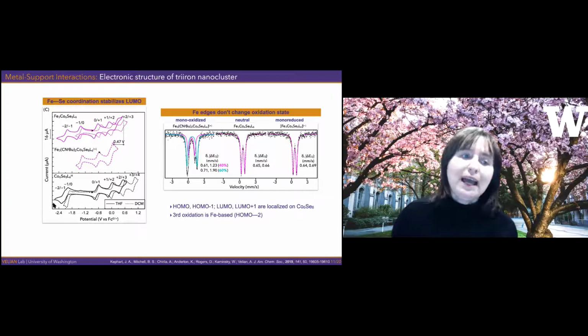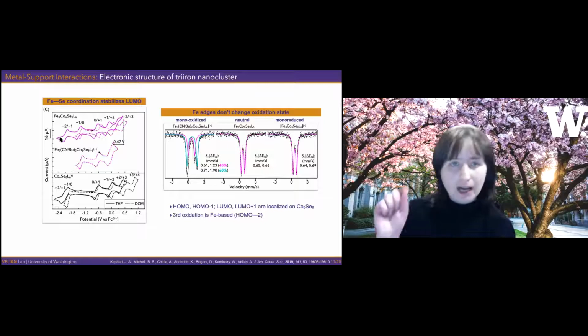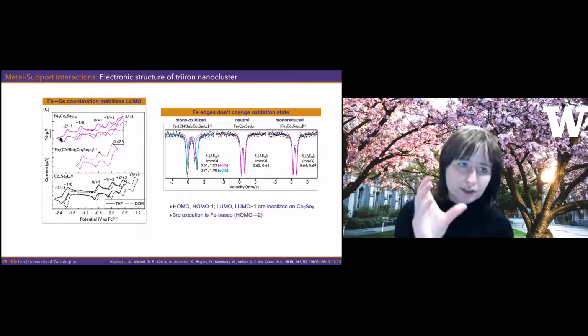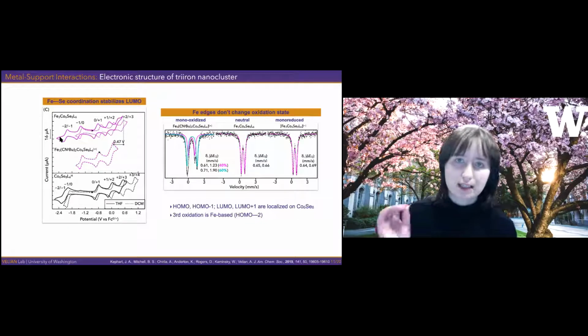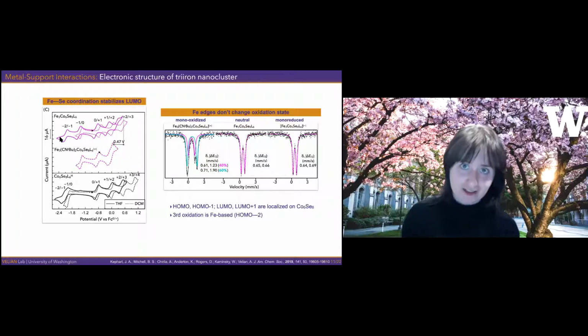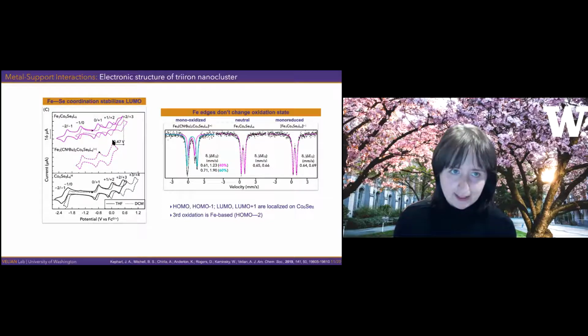Now, what happens if we put the irons and have these irons on the surface of the cluster? How does the electronic structure change? There are a couple of things going on. One is that a lot of the features stay pretty much the same. Like, for example, the second reduction and some of the oxidations seem to resemble very nicely the cobalt selenide core. However, the most drastic change occurs in this first reduction event.